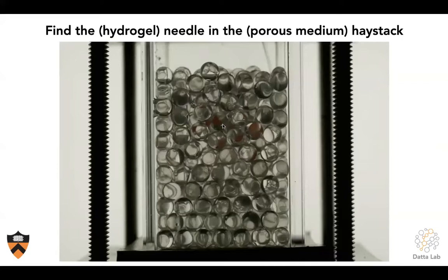And this is where we use a trick that we've refined over the years and we've applied in many cases. What we did is we formulated an aqueous-based solvent that the hydrogel still likes and swells up in, but which has the same refractive index as the glass beads making up this packing, right? And so what happens when you infiltrate this packing with this solvent is everything becomes transparent, right?